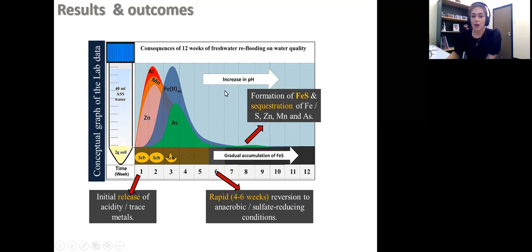And then again, similar to other trace metals, arsenic also disappeared, which showed that it was probably sequestered inside the structure of newly formed iron sulfide minerals in our experiment. So with these two experiments that I already mentioned, we got some good ideas. We knew that the oxidation of the surface sediments of the freshwater reflood as the surface of wetlands can occur in a very short period of time.